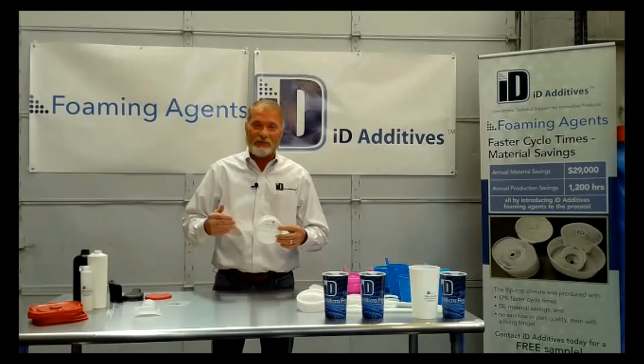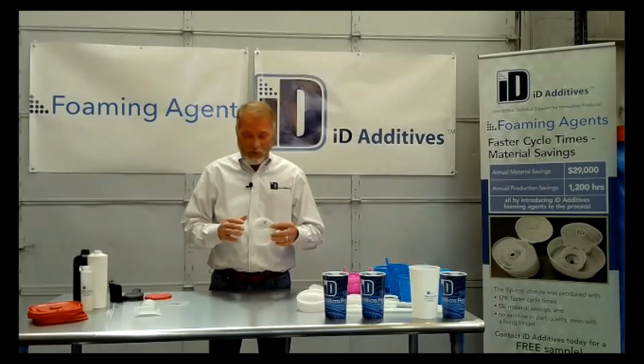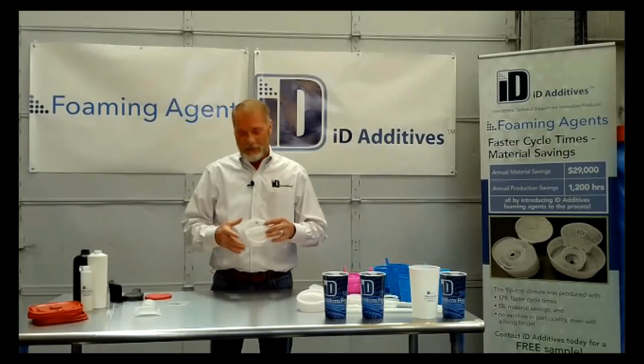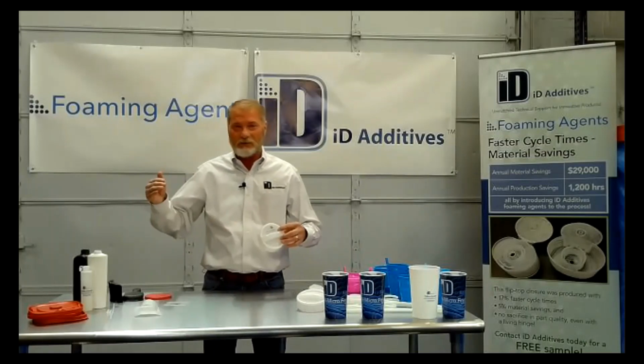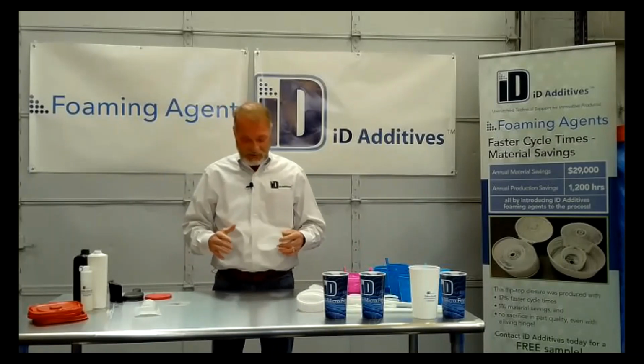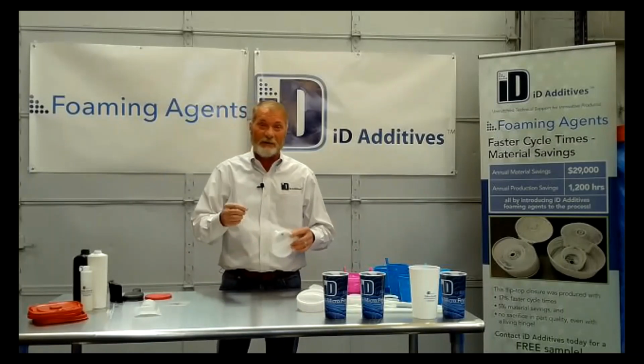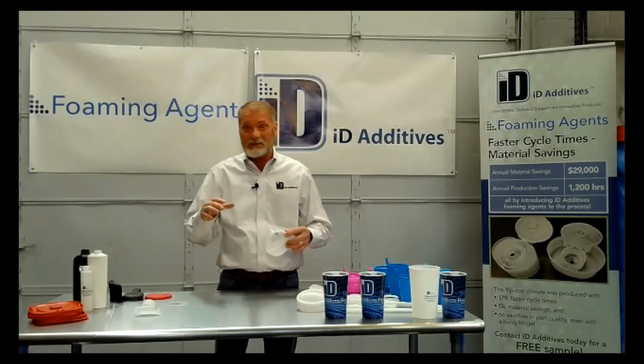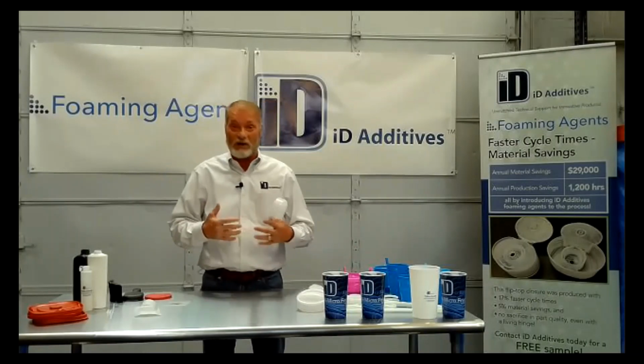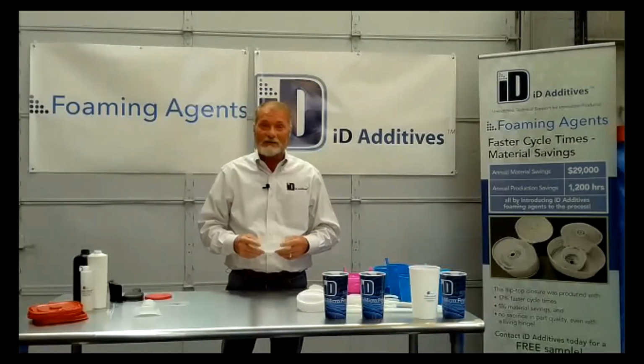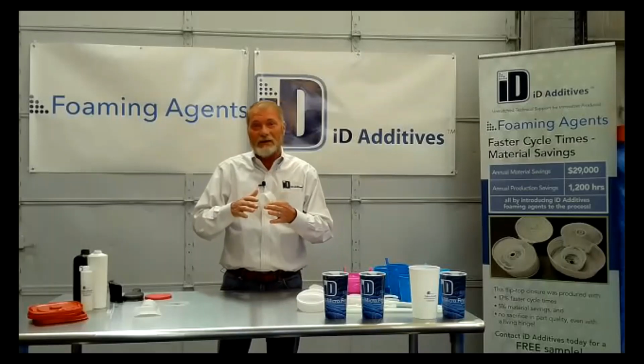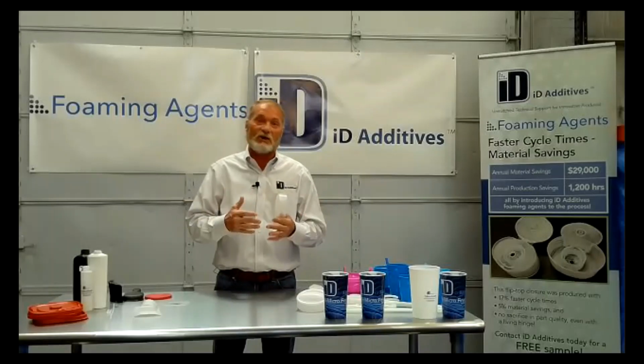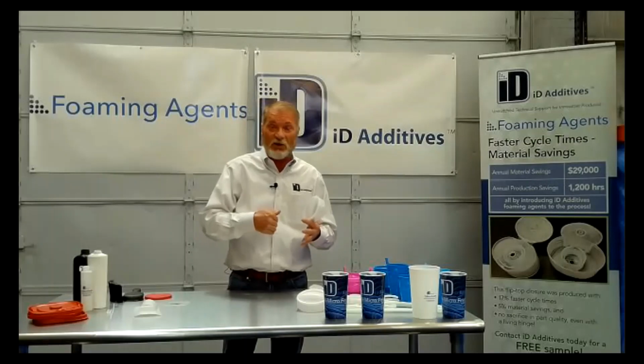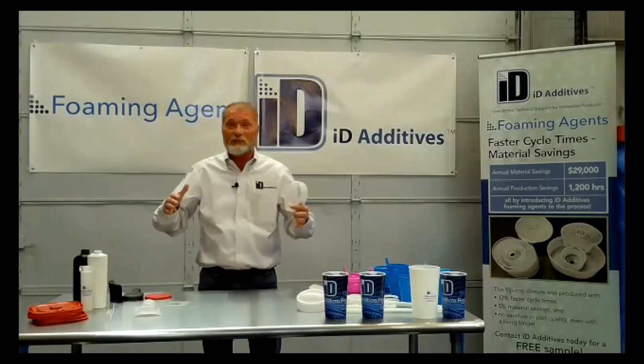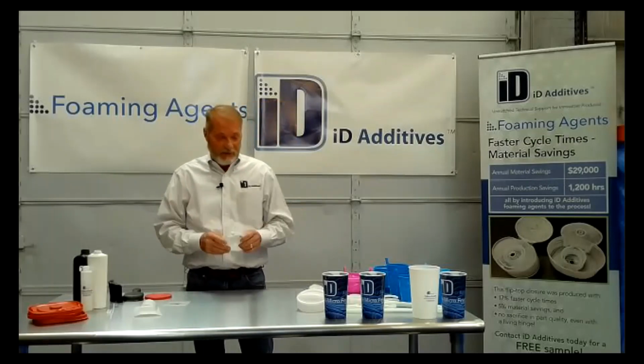So injection velocity is very important, because foam, when you're doing our microfine cell in a thin wall application, foam really doesn't want to come to the surface. It wants to go the least path of resistance, and that's right into the core. If you've got some ribs or some boss areas, things like that, that's where the foam naturally wants to go. And that velocity keeps most of the foam in the middle, and it doesn't push it to the outside. So if you start packing it, or you inject slow, it'll push that foam to the surface, and that's where you see splay.